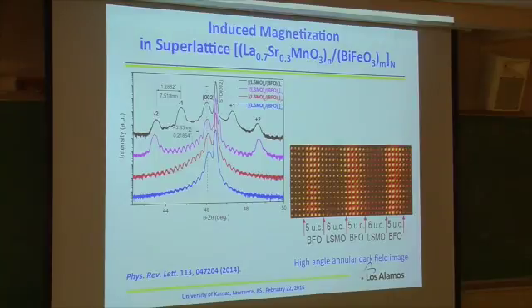Okay, people actually report this using XMCD, X-ray magnetic circular dichroism, that kind of measurement. This is more qualitative, people see that. But the question is, can you do some kind of quantitative analysis or not? Can you really tell what's going on quantitatively across the interface? So one way we did it is we said, well, let's just put a superlattice structure over here. For example, here we have a 5 unit cell bismuth ferrite, and a 6 unit cell LSMO.